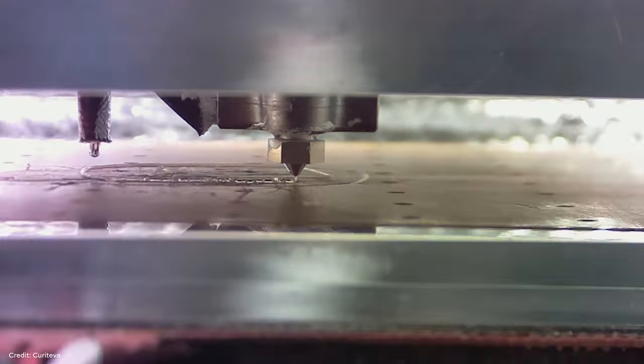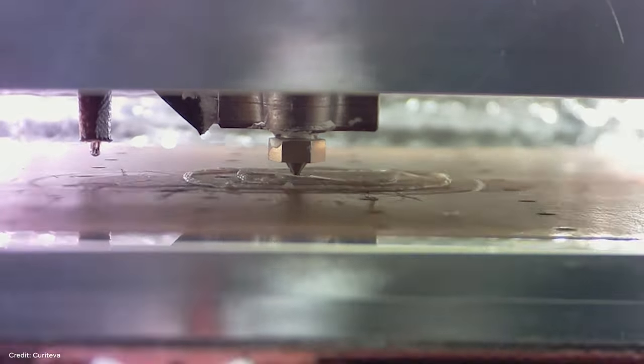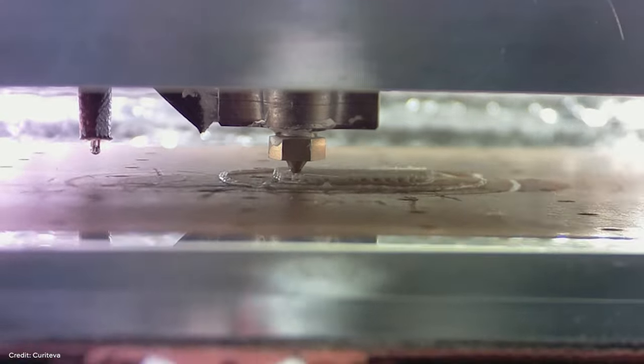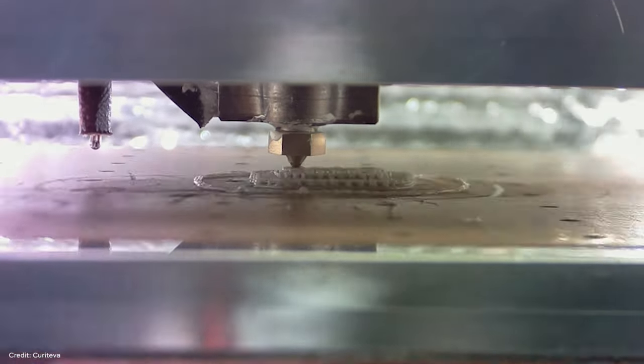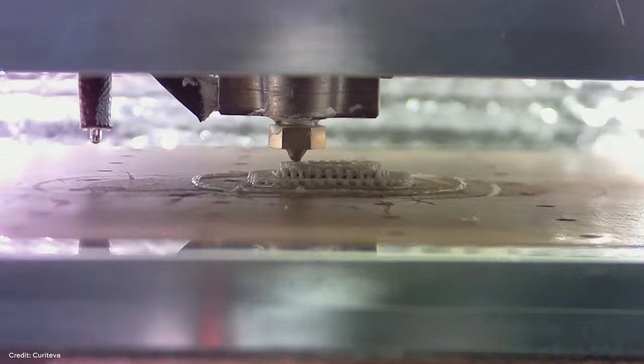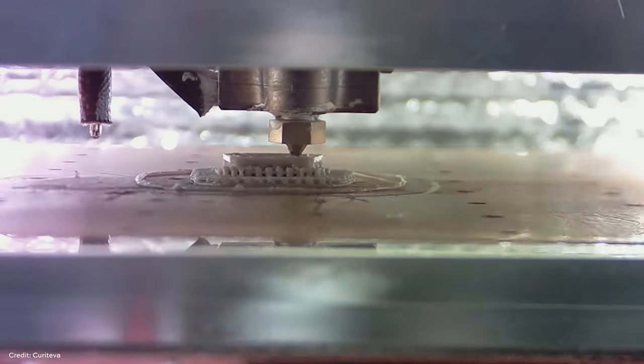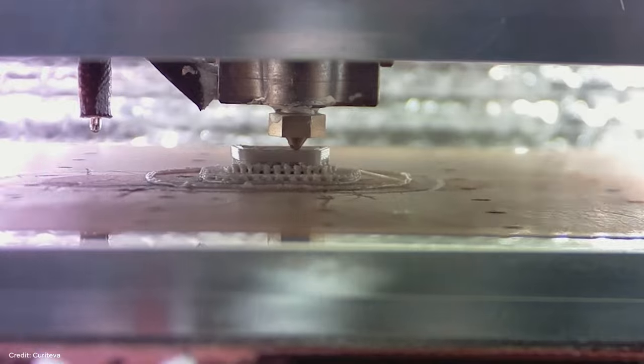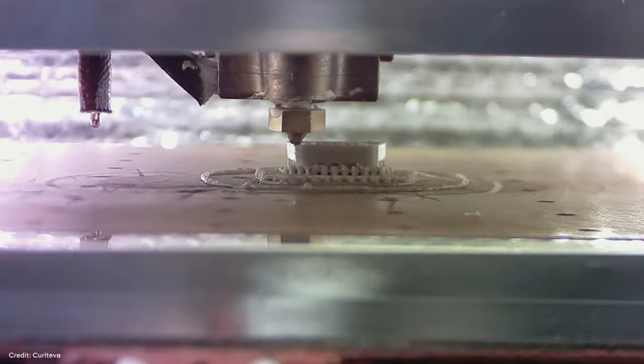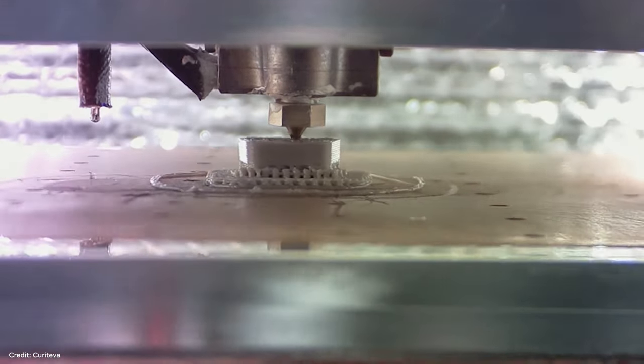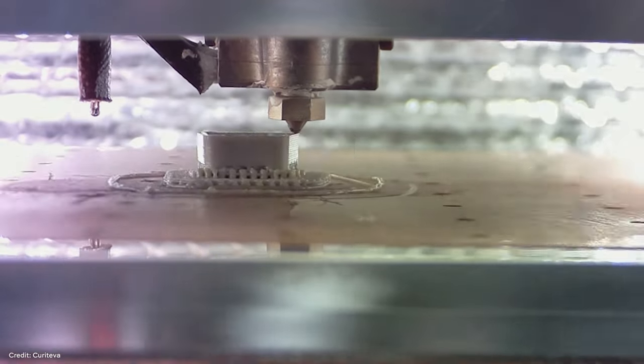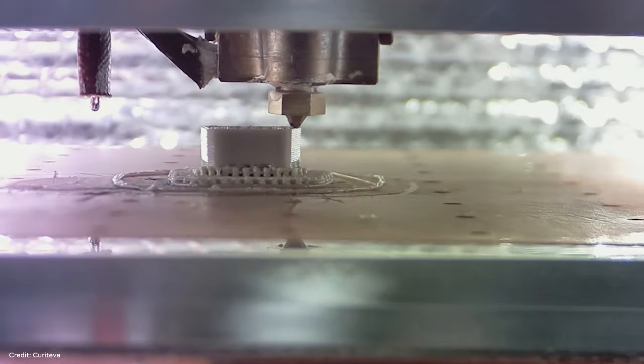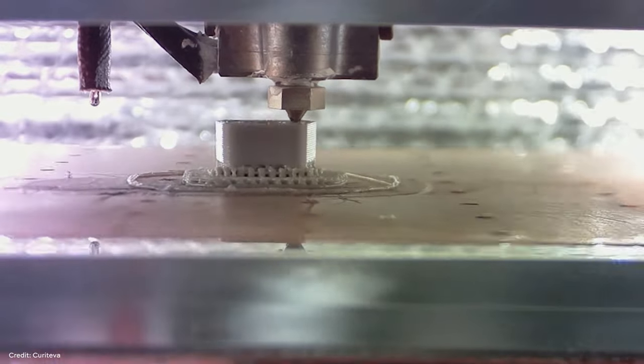The delta between the glass transition, TG, and the melt temperature, TM, is over 200 degrees Celsius. TG is roughly around 140 degrees Celsius, and TM is approximately 350 degrees Celsius. It's critical to manage the thermal history during the printing process to prevent locking the PEEK in an amorphous state versus a more desirable crystalline state. Our patented technology precisely targets the necessary heat at the active deposition layer during the extrusion.